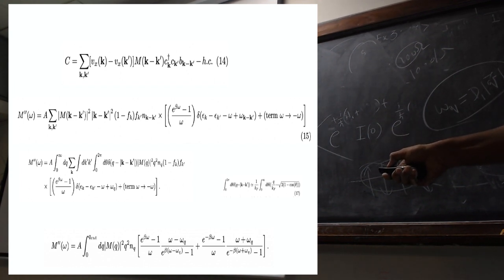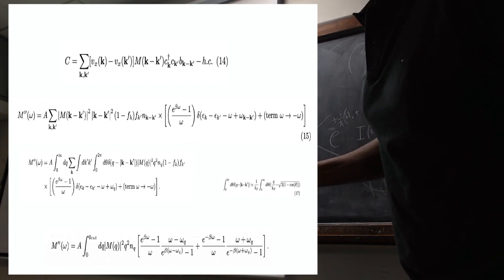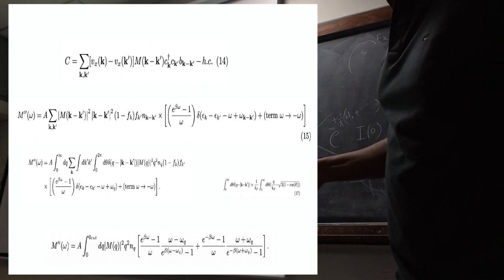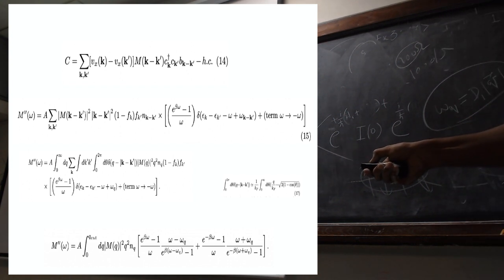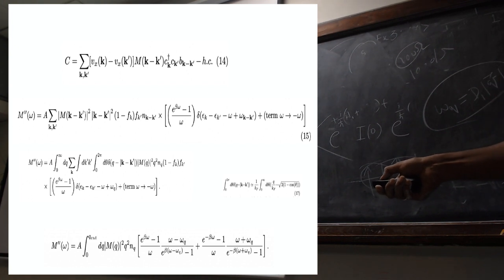Then you can simplify this k minus k', you introduce a delta function, delta q minus k', with the integral from 0 to infinity dq. Now just say that k is pointing in the z direction, k' is making an angle theta with that, and d theta is the angle. You do this integration very easily. The delta function of a function can be easily calculated. This is not very difficult but cumbersome. It takes time, maybe 20 pages of calculation. You will get this memory function.